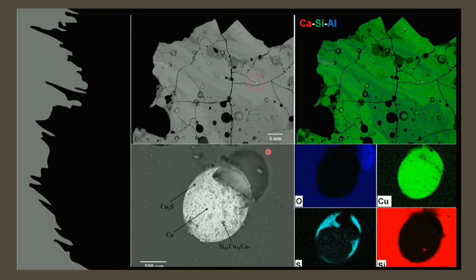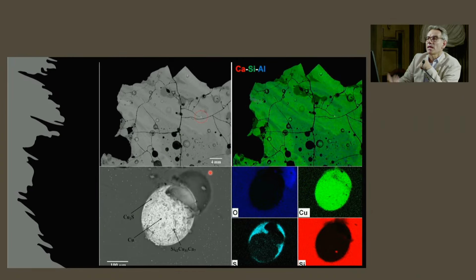At the top you can see the compositional maps of the composition of the silicate glass. It is actually a calcium, silicon, aluminum glass, which is quite common. But if you look inside the droplet, this testifies how careful you have to be in order to carry out these kinds of studies. Because if you don't look carefully, it seems that it is a copper droplet, and indeed, if you look at the chemical maps, it is mostly copper.